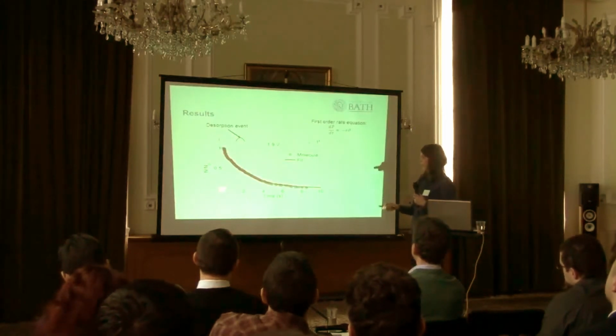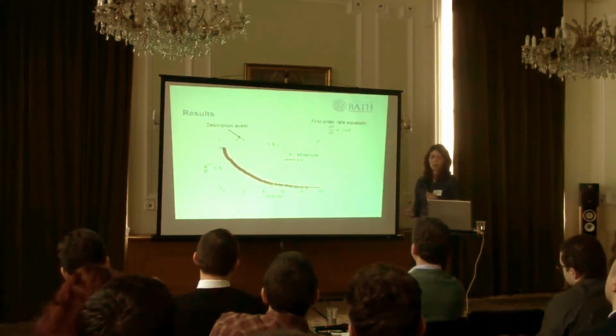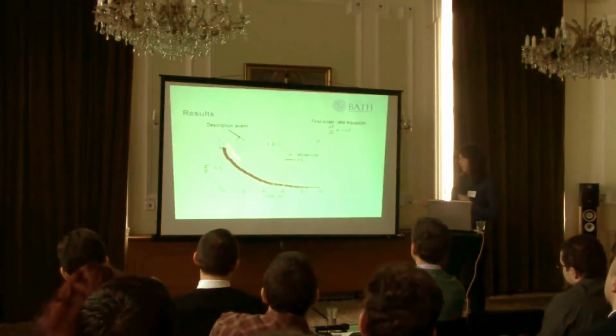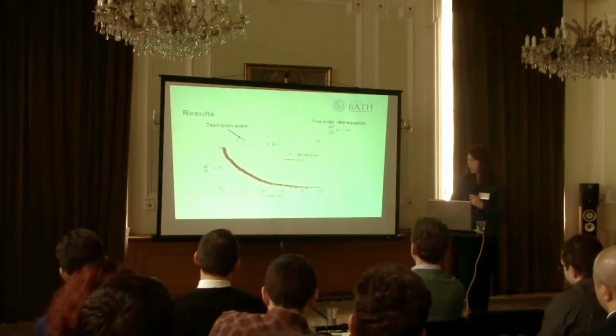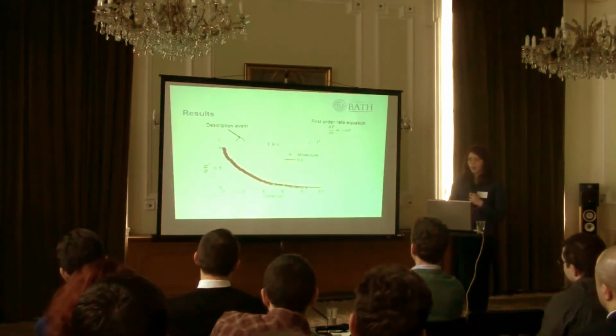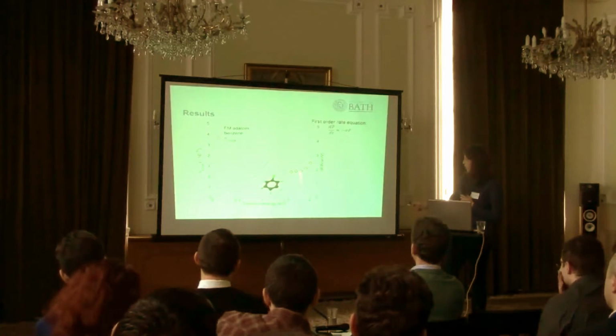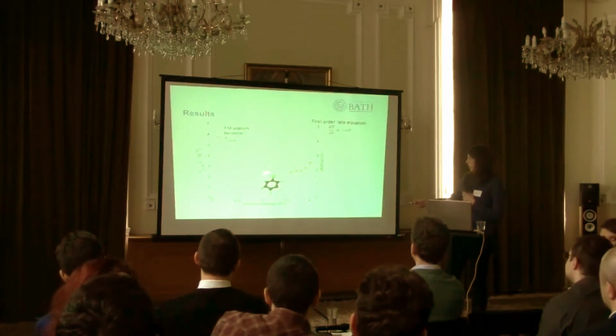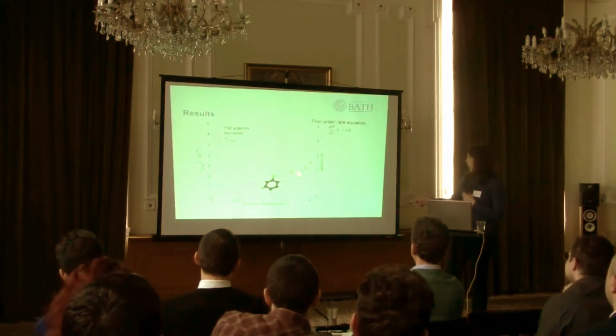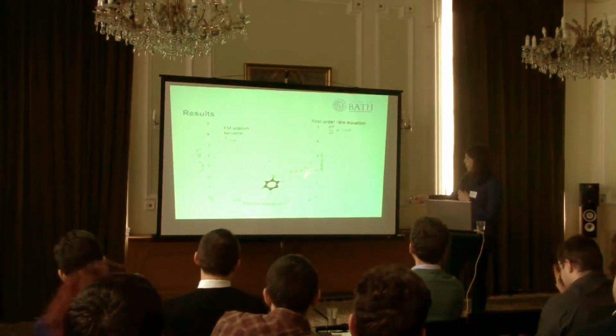It has left the surface, and the measured time is related to the number of electrons that we get. And it is really nice to fit an exponential. This basically tells us whereabouts local manipulation starts taking place, and you can just about see that there's a threshold that starts kicking in around here. So these are the electronic states of the sample and the molecule, and you can see that there's an onset in the electronic states of the sample.